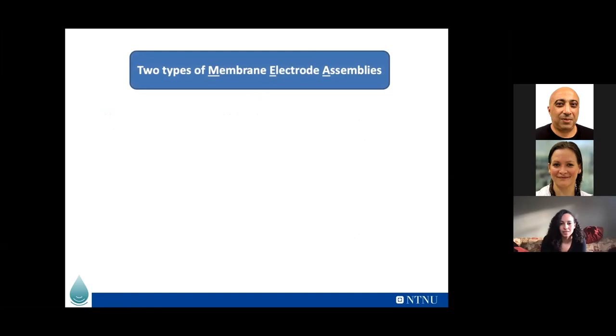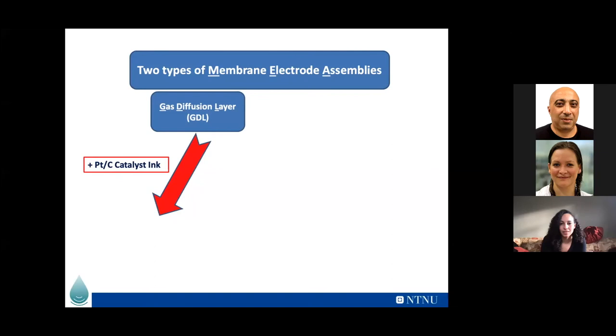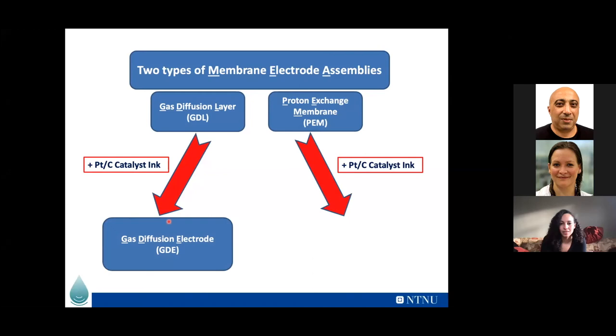So for the last bit here, I've got about 5-6 minutes. There are different ways to produce your electrodes, could it be for fuel cells or electrolyzers, mainly PEM water electrolyzers and PEM fuel cells. You could use a gas diffusion layer where you deposit your platinum-supported-on-carbon catalyst ink, and you end up with a gas diffusion electrode or GDE. Or the other option is to use your membrane, which separates the anode side from the cathode side catalyst layers, and you deposit your catalyst ink straight onto this membrane, could be Nafion, and you end up with a catalyst-coated membrane or CCM.